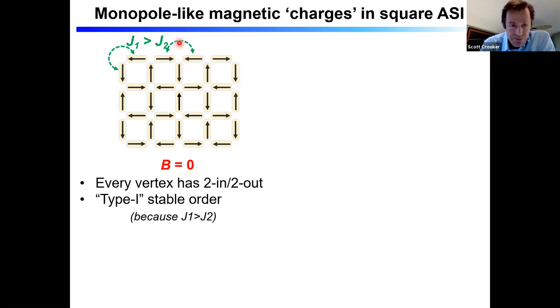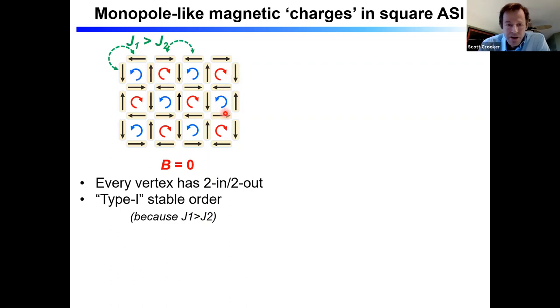And because J1 is bigger than J2, at zero magnetic field, you can easily convince yourself that this is the stable ground state. So each vertex has two in and two out. So I've got two in, two out here. I've got two out, two in here, two in, two out here. This is what we call a type one order, okay? Because this J1 coupling is larger than J2. Some people call it a chessboard or checkerboard order because this plaquette rotates counterclockwise, this one clockwise, counterclockwise, clockwise, so on and so forth.